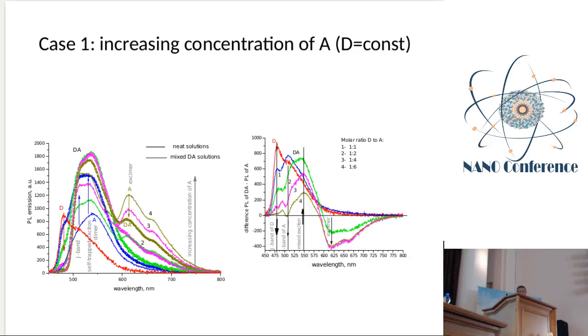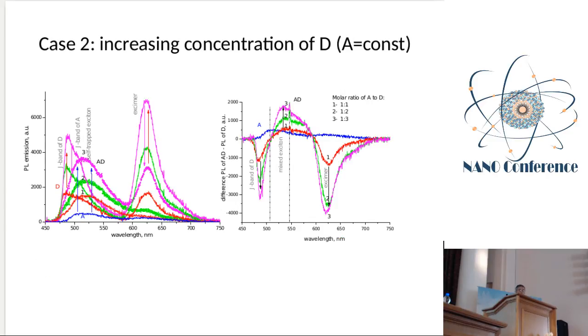So the second case, when we increase concentration of donor in the solution with a constant concentration of the acceptor. So again, we have contribution of excimer in the neat donor solution much higher than in the mixed solutions. That means that the excimer become not so effective in the mixed solution. And this is again demonstrated by the difference spectrum when we subtract the neat donor photoluminescence spectrum of the donor from the photoluminescence spectrum of the mixed solution.